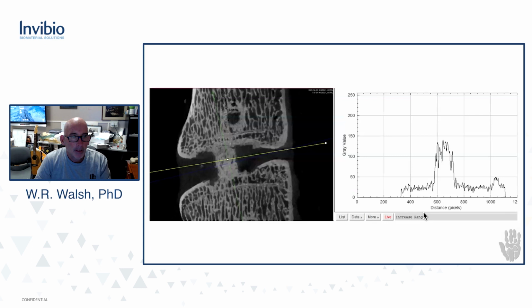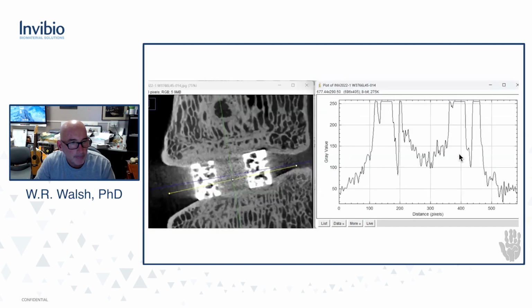So what we did, well, actually, just to finish off that thought, this is what happens if you do a profile line through PEEK in the current study. You can see this is a little bit of a grayscale value there, and then boom, that's our fusion. And if we pass the same profile line through the titanium, we peak out, that's ironic, but we max out at 255. We get something in the middle, but we're really not sure. This is the interface, right there. What's happening at the interface, we cannot really tell.